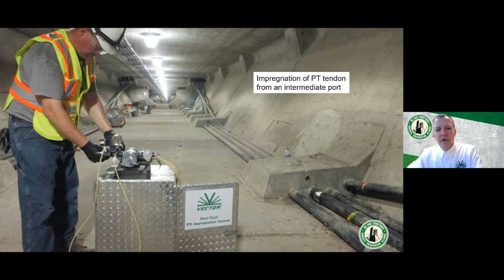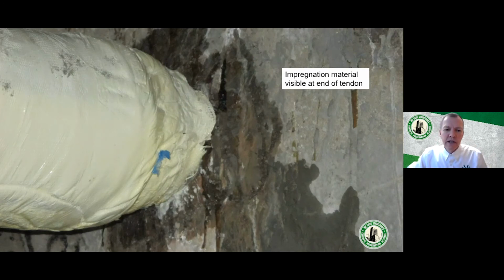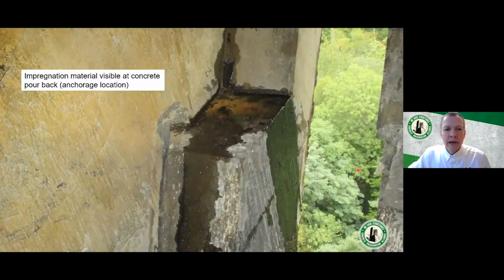And when you're pumping from an intermediate location, typically you're going to pump until the material is visibly present at one or both ends. Usually what you'll see is at the end of the duct where it goes into the diaphragm wall, you may see material starting to come out of small cracks in the concrete diaphragm wall. That's one sign that the material is there. And the other sign is that, if you've got a concrete pour back on the other side of the diaphragm, you may have signs that it's leaking out around cracks between the pour back and the concrete segment itself. So in these cases, the work was done from an intermediate location because the cost and time involved in removing all of the concrete pour back to expose the anchorages was considered to be prohibitive.